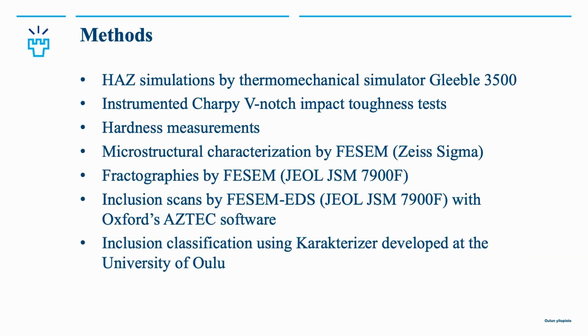And methods. On this single pass weld, we simulated heat affected zones by Gleeble, and then we measured impact toughness by instrumented Charpy V-notch test. Hardness measurements were done also, and then we did microstructural characterization and fractography studies and inclusion scans by SEM. And for inclusion classification, we used our own characterizer tool that was developed by my colleagues at the University of Oulu.